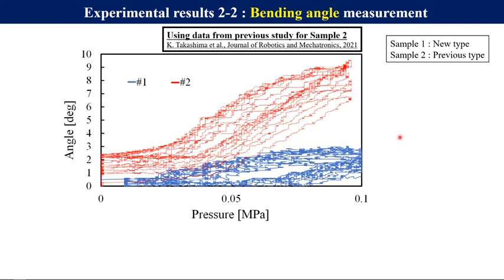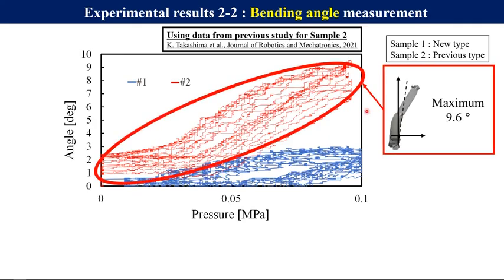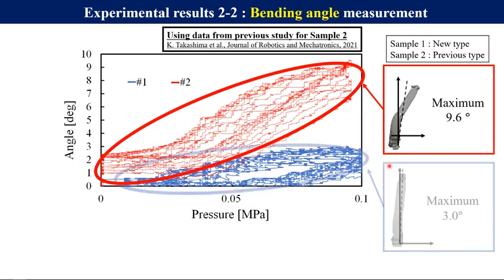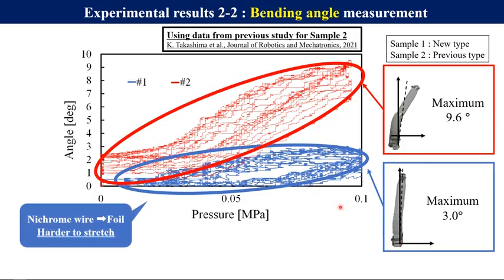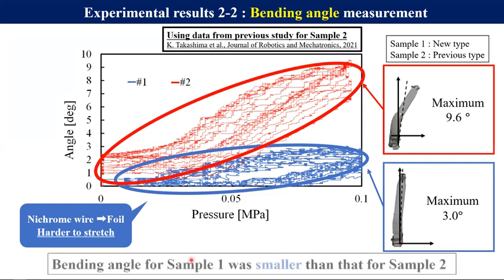This is the experimental result of bending angle measurement, and the vertical axis of this graph shows the bending angle, and the horizontal axis shows the pressure, and we used the previous data for sample 2. When it comes to the maximum bending angle of sample 2, it was 9.6 degrees, and for sample 1, it was 3.0 degrees. So, this result was also attributed to the change from Nichrome wire to foil, which increased the tensile elastic modulus. And consequently, as well as the result of the isometric test, we found that the bending angle of sample 1 was smaller than sample 2.